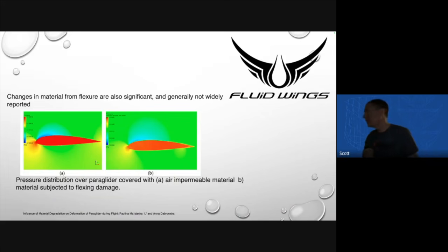So it's important to realize that this is kind of that aha moment, I think, that I want to share with you guys: the flexure damage on your fabric can be as great, or in some cases even a little bit more, than the porosity damage. So you could have a wing that has a ton of jumps and the porosity looks good, but the fabric's been flexed and you've deteriorated the fabric from loading it and wear and tear just from use, and the flight characteristics are going to change. So every time you use your wing, you're deteriorating it.